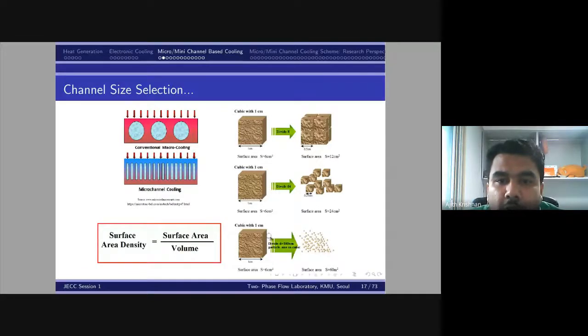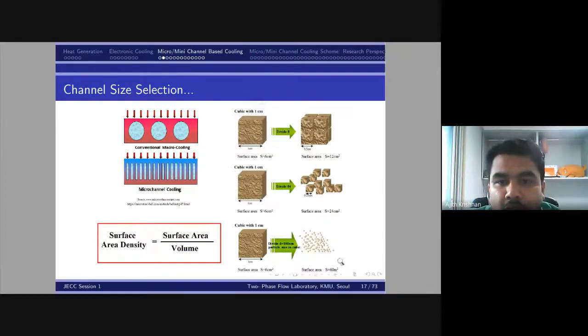Similarly, here you can see a 1 centimeter cube, which has been divided into small cubes of 100 nanometer, and the surface area has increased to around 60 meters squared, from 6 centimeters squared to 60 meters squared. See what's the increment. So there is a drastic increase in the surface area if we use miniature channels. The basic concept behind that is surface area density, that is, for a particular allowable volume, what is the surface area? Or we say surface area to volume ratio.